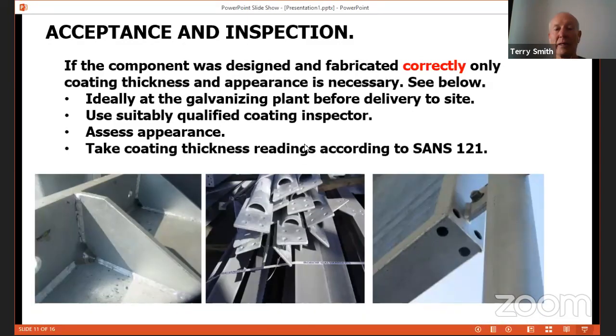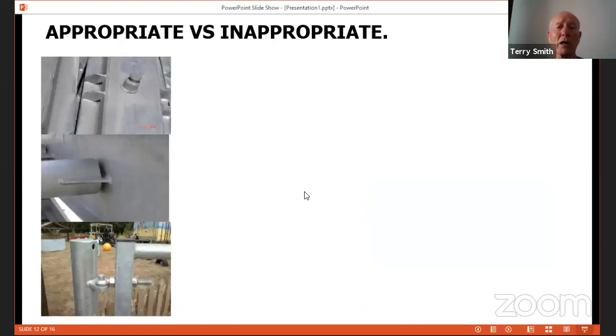And here you can see several pictures of well-designed, well-galvanized and fabricated items. These are nice big coping holes, allowing the zinc to flow through when it goes into the zinc bath. At the end of the tubes, this gusset plate has been welded inside the tube so the zinc can flow out. And the same on this one, with the holes right in the penultimate corner of the item. Appropriate versus inappropriate.